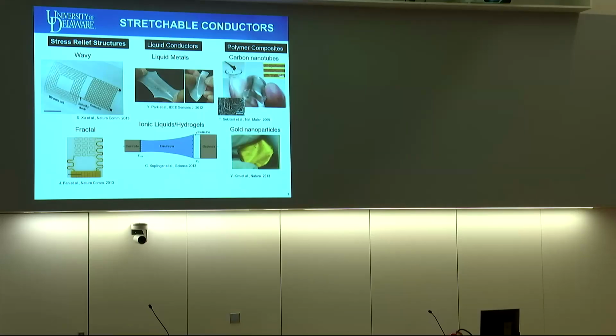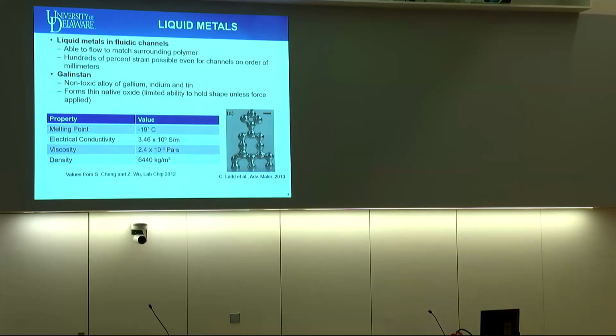So we need a balance between high conductivity and a very large ability to survive mechanical strain. Dr. Dickey did a wonderful job of introducing it this morning, so I'm not going to go into detail on the material, but one of my main conductors of choice, again, is these room temperature liquid metals, which have some very large advantages from the perspective of making current carrying devices. They're able to flow to match a surrounding elastomer, and so you can get very, very large deformations. You can get hundreds of percent strain, and you can do it even for large cross-sectional areas of traces. Because these larger cross-sections are the only real way we have to compensate for the lower conductivity in the material.